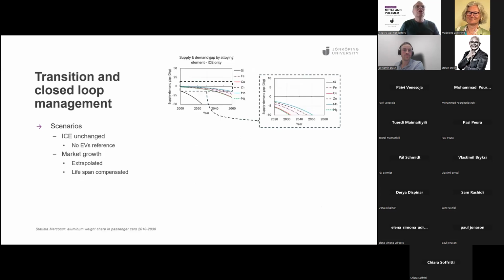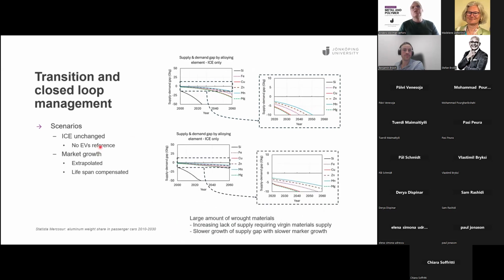So now taking another look at the combustion engines and all the alloying elements. The ones that we are thinking about are silicon, iron, copper, zinc, manganese, and magnesium. With an internal combustion engine, of course, there is a constant need. There is no change in the composition of the material. So we see that it's growing. And if we blow up this part, it is a significant requirement on these elements, and it's continuously growing. And the scenario does not really change when we do lifespan compensated material.